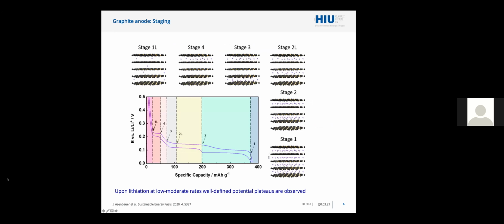How do we see this staging mechanism in practice? Well, first, we obviously can do X-ray investigation, but we can get this information also just by measuring the potential upon lithium insertion in graphite. And what we see are these typical steps, which are typical of multi-phase or two-phase processes. And these occur obviously at different potentials. And the more the graphite is lithiated, so the more channels between the layers or planes are filled, the lower is the lithium insertion potential.